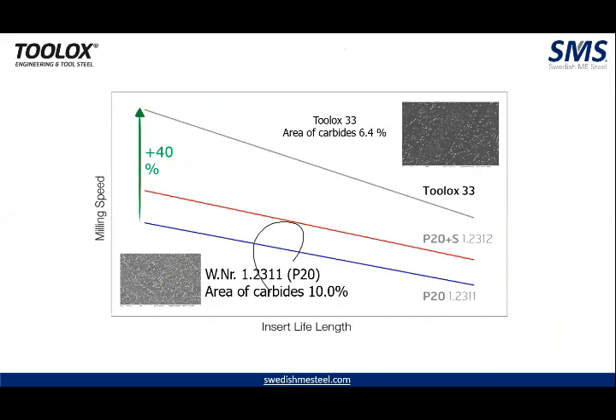In making Toolox 33, as I said, it has low carbon and the alloying element is very low along with it. So the carbides in the material are very few. Carbides have their own pros and cons. When we have low carbides, you are able to easily run your tool through the material. So with whatever tooling you use for your regular P20, if you use the same tool, you'll be able to increase the milling speed of that tool by 40%.